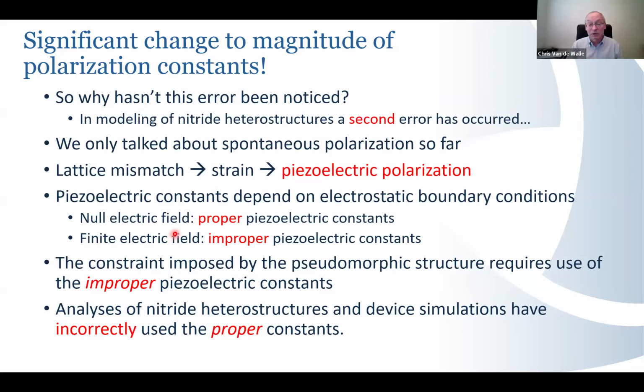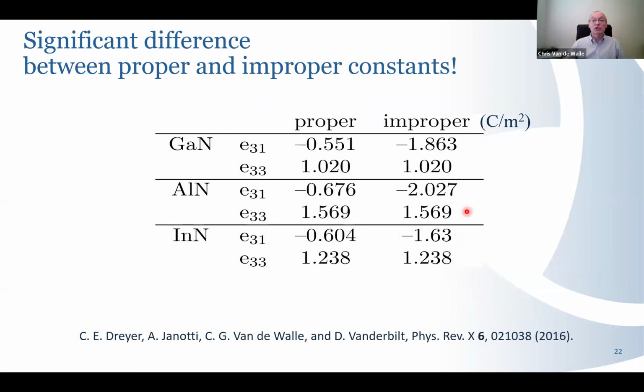Or another way of thinking about it is that we've applied a constraint. Rather than having this freestanding layer where we just push on it, in the case of our heterostructures, there is a constraint that the in-plane lattice parameter is fixed to a certain value. And within the theory of piezoelectric polarization, this is perfectly straightforward to deal with, but you have to use different piezoelectric constants, the so-called improper piezoelectric constants. And this has not been done in the device simulations to date. All those simulations have incorrectly used the proper constants. And this second error has largely obscured the first error in choosing the correct reference structure.